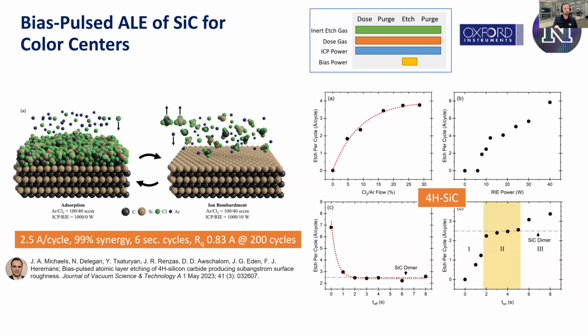So later, Julian did this on diamond as well. Diamond has a specific issue where we know, and I was talking about before, how do these devices perform? The surface roughness turns out to matter quite a bit. People do all these really aggressive acid cleanings. Well, Julian was able to modify the same process.